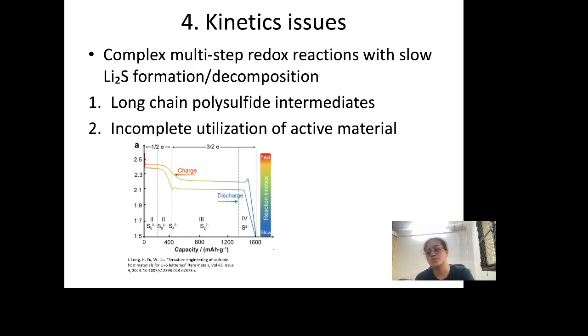And the second problem is the incomplete utilization of active material, which stems from a more thermodynamic kinetic aspect, which is that the transition to lithium sulfide, Li2S, is a solid-liquid-solid transition, and there is a formation of Li2S2 compound, which precipitates out of the liquid phase sometimes. Because sulfur is our active material, and we have an unwanted product which contains sulfur that precipitates out in this reaction, it leads to the loss of our electrode's main active material, and that is not what we want, and that is also a problem. That also needs to be dealt with before we can go on and commercialize lithium sulfur batteries. So in conclusion,